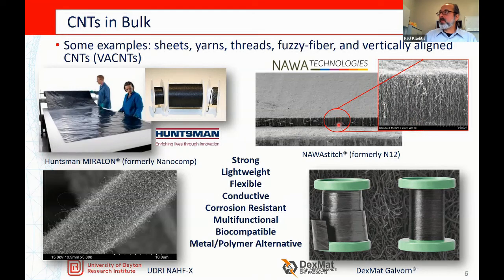It's about, let's see, a human red blood cell. One of your human red blood cells is about 7 micrometers, or in slang, microns, in diameter. So this height is about 3 of your red blood cells stacked up end to end. And we have to control that height very precisely. And these carbon nanotubes are used for putting in between layers of composites and strengthening the composites. And I'll show you that in a second.